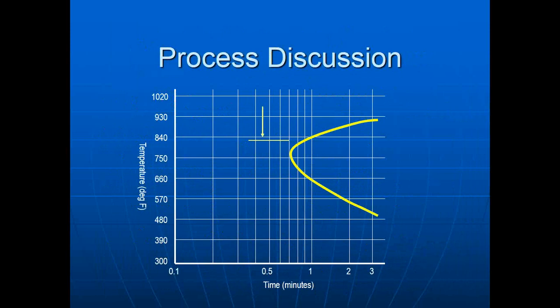So our entry zone is the place where we can manage any geometry issues. Again, from a property standpoint, faster is better. If you have a solid rod you're running through this quench, run all the quench you can. Fine. But when you struggle with geometry problems, you go to the entry zone of the quench and you turn down the performance of the entry zone in order to minimize the deformation of the geometry.